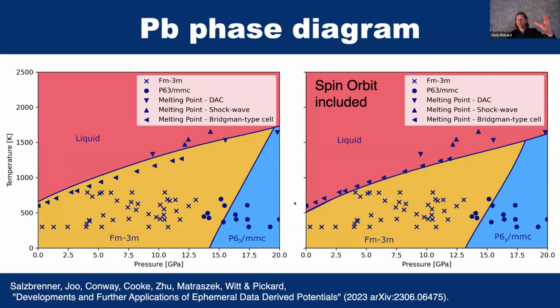You need a big chunk of liquid, a big chunk of crystal, and you need to do a long molecular dynamic simulation. This is just too expensive from a pure DFT point of view. And so if you look in the literature, there are not many phase diagrams computed for elements such as lead. But what you see here are phase diagrams computed. Essentially these points can be generated on a laptop and compared with experiments.